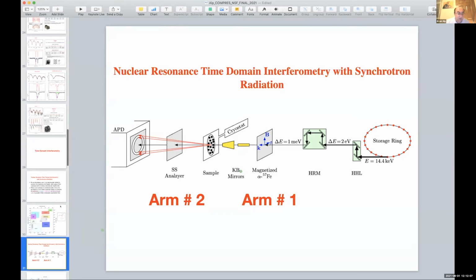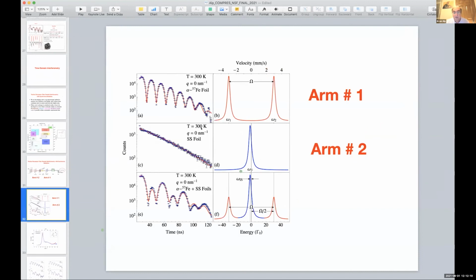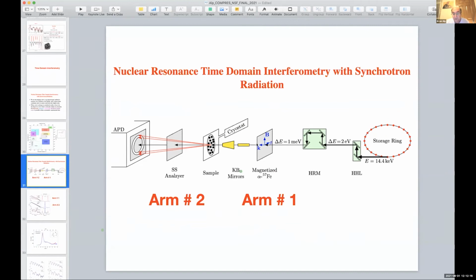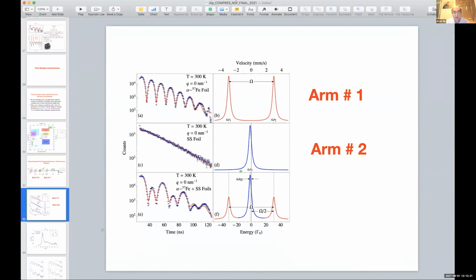Now those of you who are familiar with it will immediately recognize that the iron foil, when it is magnetized in this form where the B is perpendicular to propagation as well as the electric field vector, will give you a two-line spectrum, and it will give you a beautiful beat pattern like this, all right, where you have a continuous decay on an exponential scale. If you have a single line like stainless steel, you have a pattern that goes like this because there is nothing to beat against. If you put the two together, because of the long coherence length, these will interact and you will get a low and a high and a low and a high kind of pattern.